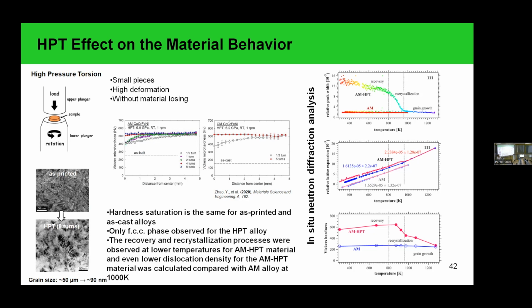Also, in these studies we investigated only the 4-component system, but considering further research, when we add aluminum or aluminum titanium, it is brittle material. And we can apply this technique, for example, to analyze whether it is possible to use it as a chemical homogenization process. In this case, we deal with brittle materials, and high pressure torsion can be more suitable than, for example, rolling, which would just fracture our materials and not allow high deformations. Okay, thank you.